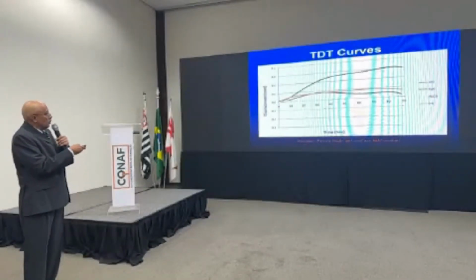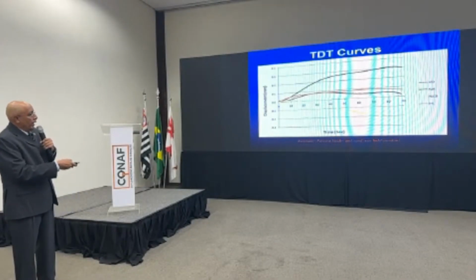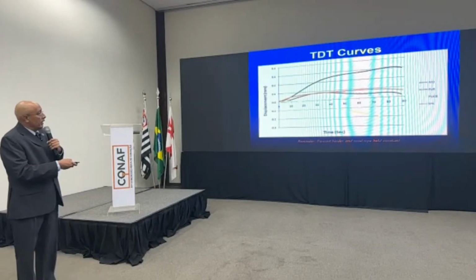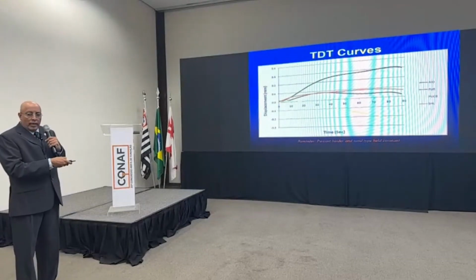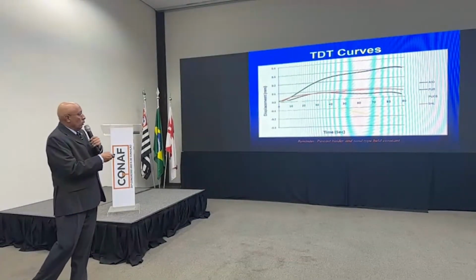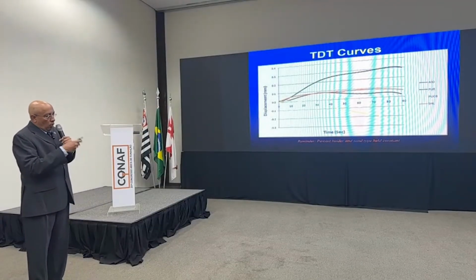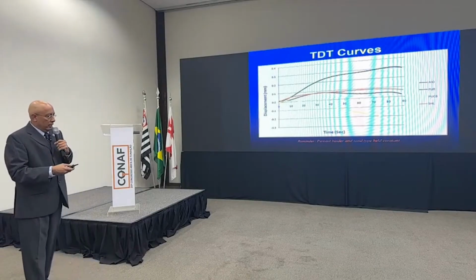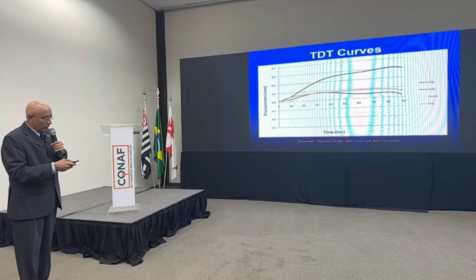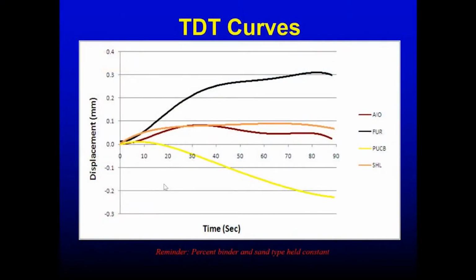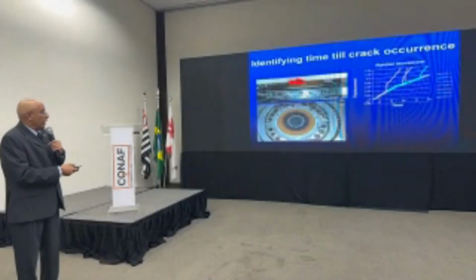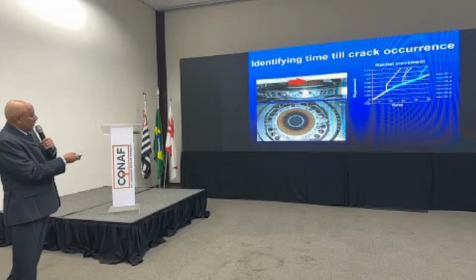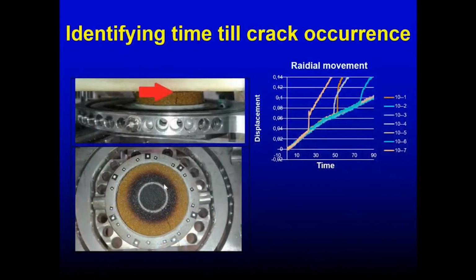And what we see from that control experiment: from the origin, the vertical axis shows the displacement or distortion, and this is time as a function of temperature. So we are testing at a steady state, and we are looking at where the casting will solidify. We don't want too much movement, nor do we want cracking. But what we see is that the thermal distortion test can distinguish between the different systems because of a thermomechanical signature, with the percent binder being held constant as well as the sand. So we know that the issue of distortion is more a cause of the chemistry rather than anything else. And if there is a crack propagation during the test, it is indicated by an inflection point.